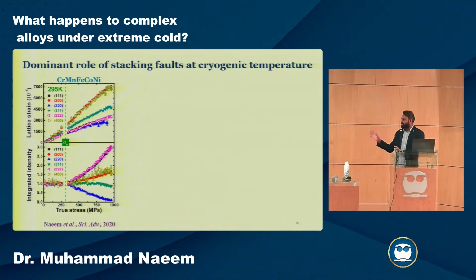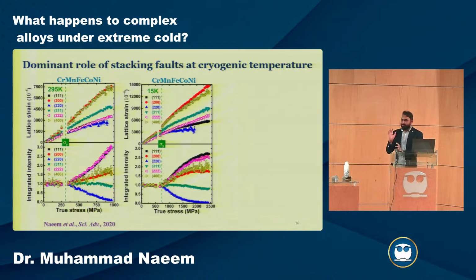I would not go into too much detail about this because I think it is too technical. I would just like to give an overview of which kind of information you can obtain from it. We can get the lattice strain, which is the upper panel, where these are different orientations or different peaks and how their relative position changes with stress. The bottom panel is what we call texture, represented here with normalized peak intensity. This is typical for FCC, where grains rotate towards 111 and move away from 220. You see the 111 intensity increasing, while 220, the blue one, is almost diminished at the end. Now, if we go to low temperature, we see some difference.